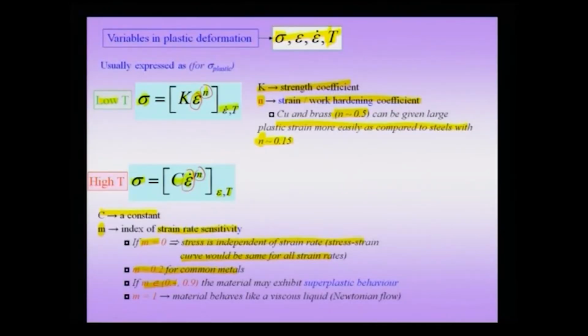If m is in the range of about 0.4 to 0.9, the material may even exhibit superplastic behavior. We will of course see what superplasticity is and under what condition we will obtain it later, but essentially superplastic behavior implies that you are getting very large elongations, even of the order of 400% or 500% or 1000%, which is not seen for a normal material like steel or even for aluminum.